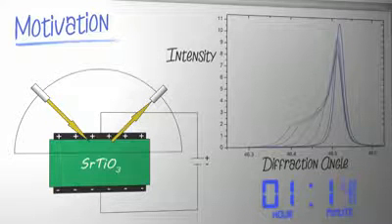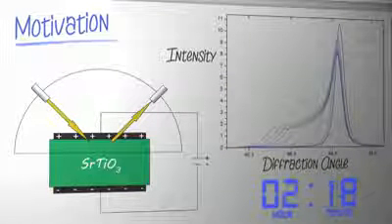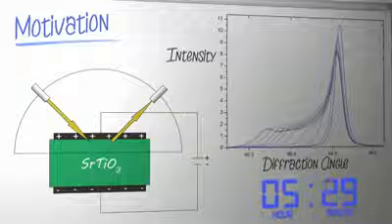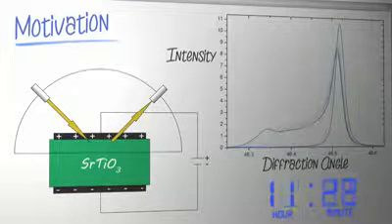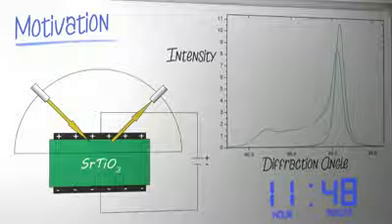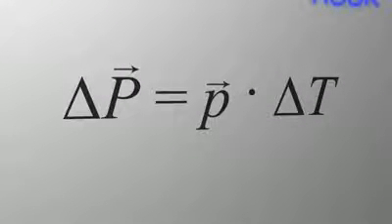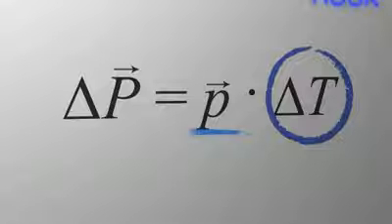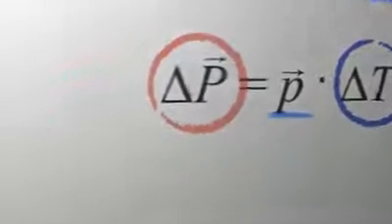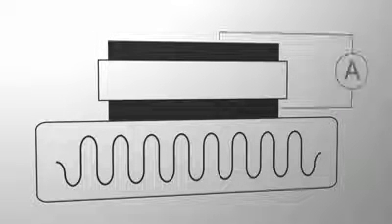The developing new phase is referred to as the migration-induced field-stabilized polar phase, in short MFP phase, which remains stable when an electric field is applied. It shows a polar distortion of the original cubic lattice and hence may be pyroelectric. But how can we measure the assumed pyroelectricity? The important parameter is the pyroelectric coefficient, calculated by the thermal stimulation of the sample and simultaneously measuring the polarization change. The sample is placed on a programmable heater and connected to an ampere meter.